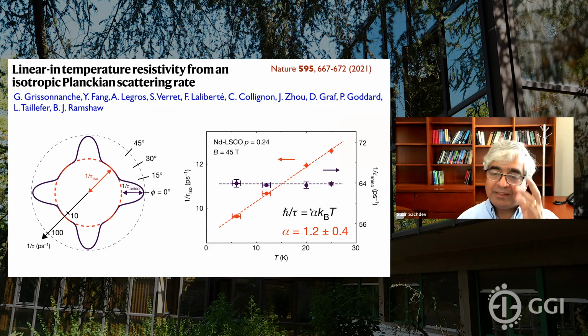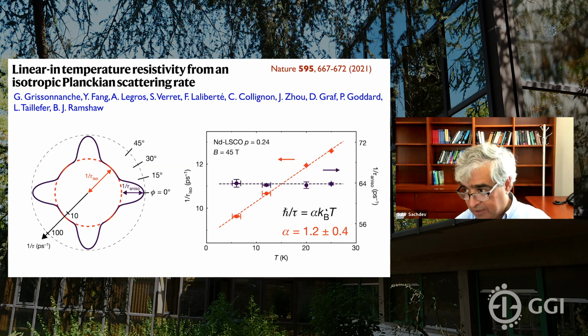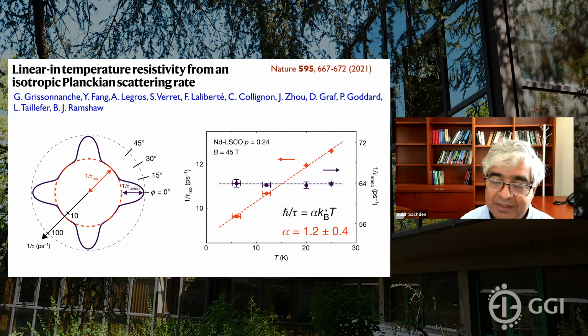So that's really quite amazing because these different materials I've shown you have very different natural energy scales, by orders of magnitude, but yet this time is just given by temperature. The natural energy scale of the interaction doesn't seem to appear at all, which seems very counterintuitive because in the quasi-particle theory, the scattering time is entirely dependent on the strength of the interactions. So there's some kind of scale invariance, which suggests that you should be looking at some scale invariant state of matter, and that will play an important role in my discussion.